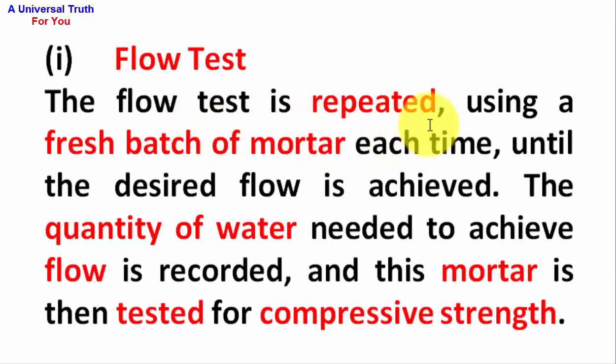The flow test is repeated using a fresh batch of mortar each time until the desired flow is achieved. The quantity of water needed to achieve flow is recorded, and this mortar is then tested for compressive strength.